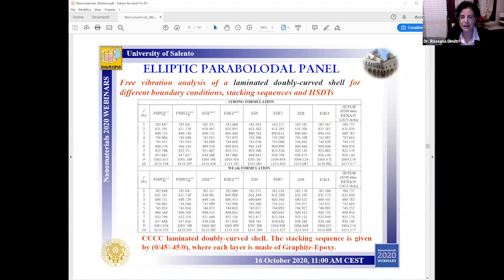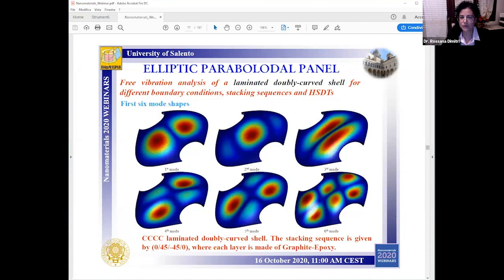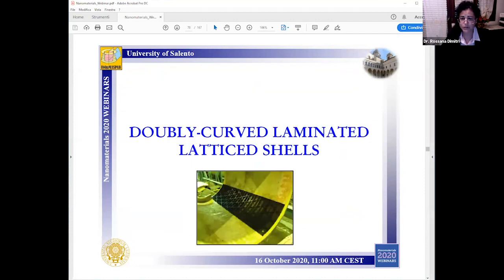And here are the results for a completely clamped doubly curved shell structure, where each layer is made of a graphite epoxy material with a stacking sequence 0 plus minus 45. Both the strong and the weak formulation get very accurate results compared to the classical 3D FEM elasticity solution. So this proves once again the accuracy of our predictions, which are also plotted in terms of mode shape in line with the selected boundary condition.